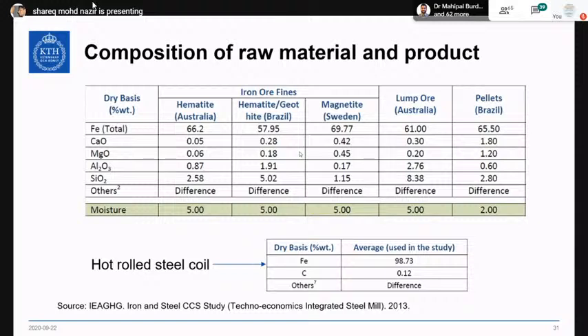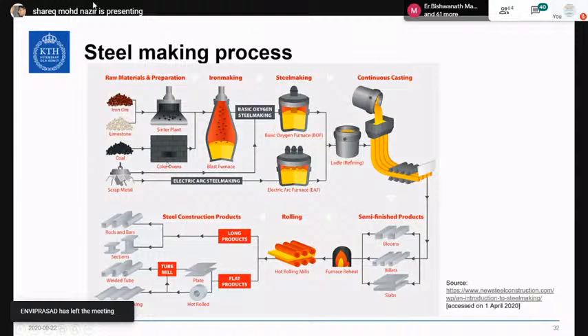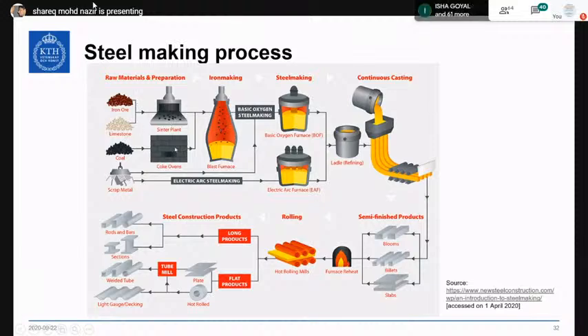So in steel, the iron ore needs to be treated to produce hot rolled coil steel. We have around 66% iron in this ore, for example, and we need to go to 98.73. It's basically in the form of iron oxides. So your iron oxides need to be reduced to iron. And you do that with the reducing agent, and that is coal in the steel plant, coke in the steel plant. So if you just try understanding the process, we have iron ore and limestone, which is sintered, fed to the blast furnace along with coal, which is passed through the coke ovens and then fed into the blast furnace along with the ore to reduce the ore.